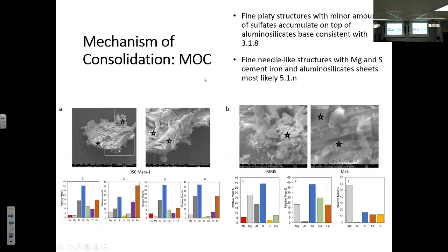You can see that the needle-like structures are much more well incorporated with the sample, and that it corresponds to literature. We found out that these needle-like structures are more of the 5.1.n phases. So this is where we find out, okay, why were we seeing that huge difference in compressive strength between the Mars and the lunar samples?